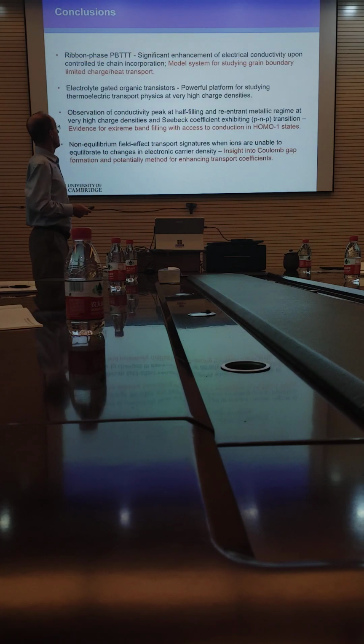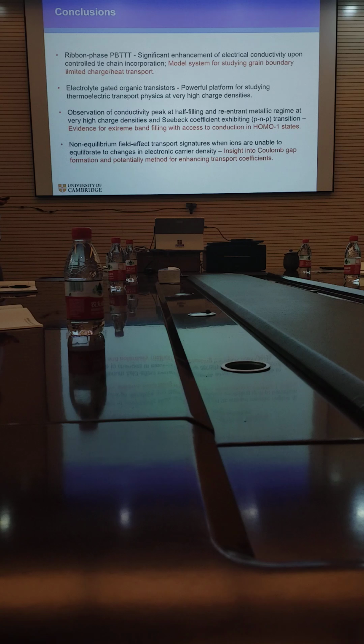So with that, I want to conclude. I hope I've shown you that it's interesting to study polymer model systems for understanding their thermoelectric physics. This ribbon phase PBTTT is quite a controlled model system that allows us to study grain boundary limited transport in these systems. The OECT is a powerful platform for studying thermoelectric physics. I've shown you that it allows us to study very high doping levels in some polymer systems, where we can see evidence that it's possible to completely empty the valence band and populate holes into the next level down, the HOMO-1 state. For those of you who are familiar with inorganic semiconductors, that would be completely impossible.